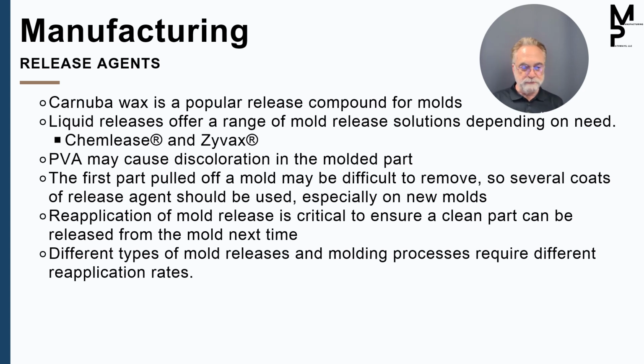And as we discussed, reapplication of release is important. We've got to get it at the right time, but if we over-apply release, we can get to the other side and get something called pre-release. So one side of the problem is parts sticking in molds, which is a bad outcome. The other problem is if the part comes out of the mold before we're done laminating. That's another problem called pre-release, which can cause the part to distort.